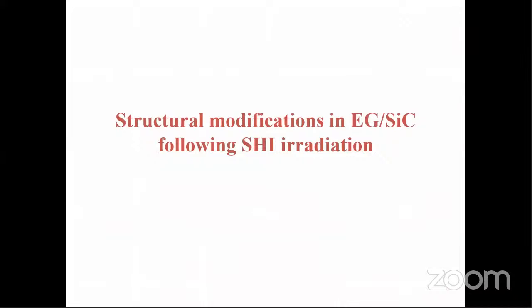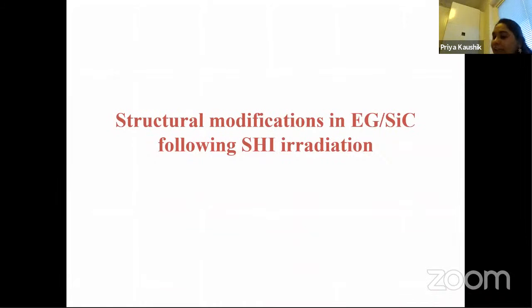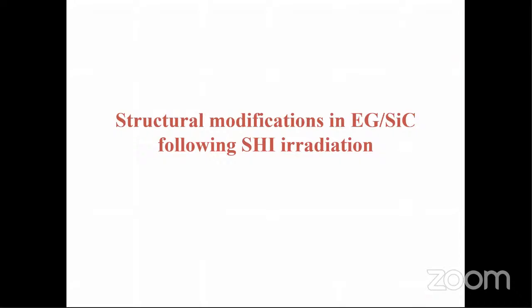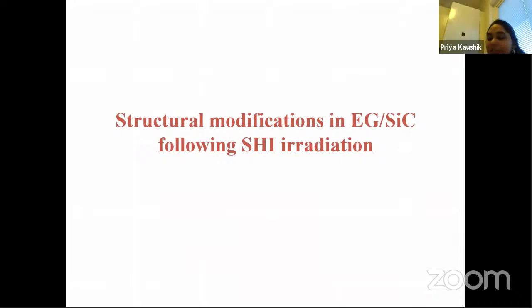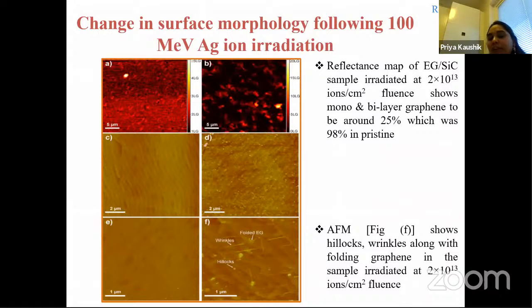Now, I am going to discuss today just the swift heavy ion irradiation. Although we have done low energy ion implantation, just to give a glimpse of how low energy ion implantation results in surface modification and in application. So we have used epitaxially grown graphene, and we have used 100 MeV silver ion irradiation.